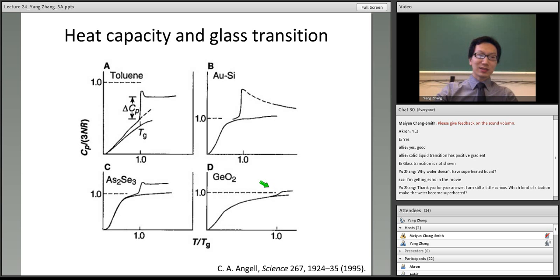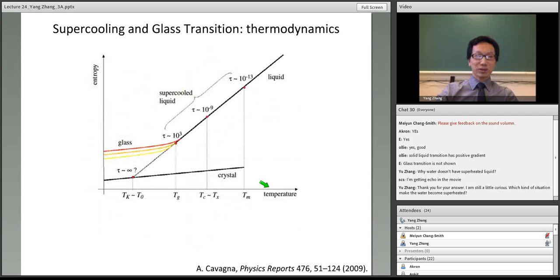Now, if we integrate the heat capacity, we can get enthalpy. So in the next slide, I want to show you either entropy or enthalpy or volume. We can plot all of them versus temperature. If we start from a liquid and cool it down, at a certain point, most of the time, the liquid will undergo a first-order phase transition and crystallize into a crystal, like here. Tm here is the melting temperature. When the liquid goes into the crystal, the entropy, enthalpy or volume of the system just follows the crystal behavior, this bottom line from here to here. Okay.